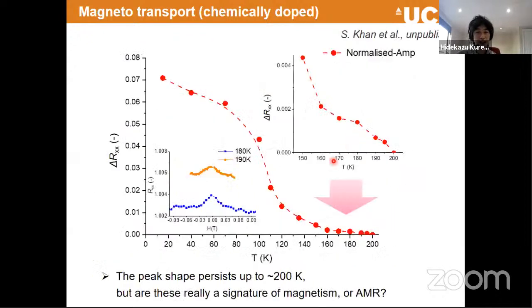So then I just measured, or this is some plot of the height of this peak. Again, at this stage it's not clear whether this represents magnetism, but it's nice to plot. And then we plot it as a function of the temperature. That reduced as we increased the temperature, and then pretty much just disappeared when we hit 200 Kelvin. So that's what it is. And whether this is related to the magnetism or not, I will come back to it later, but this is what we observed.